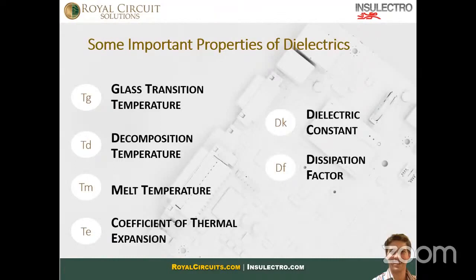But things change when we put them on a flexible substrate that's using polyimide. We change the glass transition temperature of the material, which is the point in which the material changes its expansion rate when exposed to some kind of thermal event. The decomposition temperature is the point in which materials just begin to break down. Polyimides, which are used for our flexible substrates, don't really melt. They just decompose when you start getting up to around 800 Fahrenheit. And like I mentioned before, the coefficient of thermal expansion, or ppm per degree C, is significantly less when we look at polyimides as well.